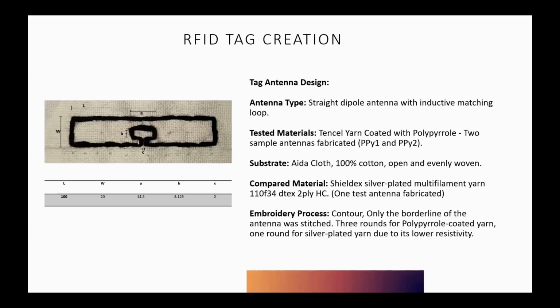Now that we have the yarn, we need to make the antennas. In the figure, you see this is the antenna geometry that we have chosen, and this is a straight dipole antenna. And with these polypyrrole-coated yarns, we made two sample antennas. One is with PPy1, one is with PPy2. The substrate used is Aida. This is 100% cotton. It has holes in the substrate, which makes the embroidery easier, and at the same time, the coating does not get removed while embroidering. And the process used was only the outside geometry of the contour, so we get the most amount of performance with the least amount of materials.